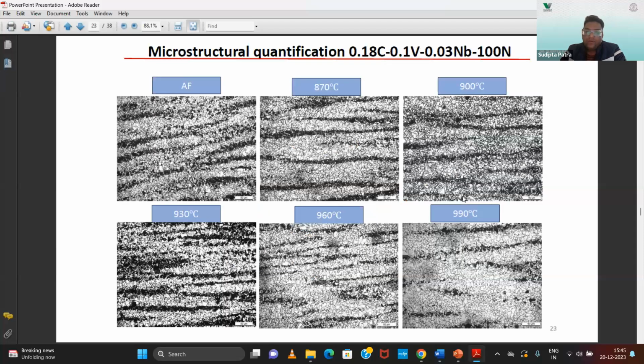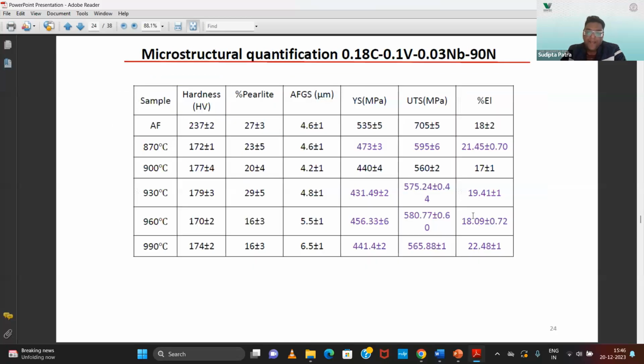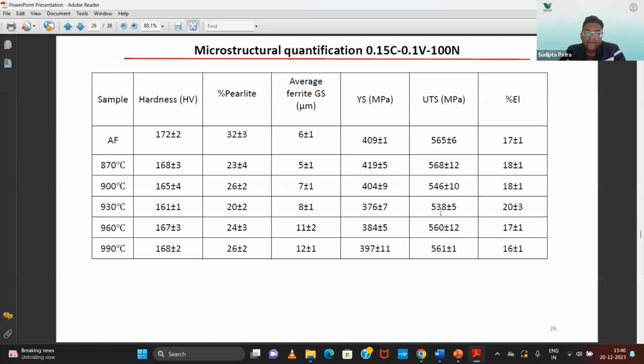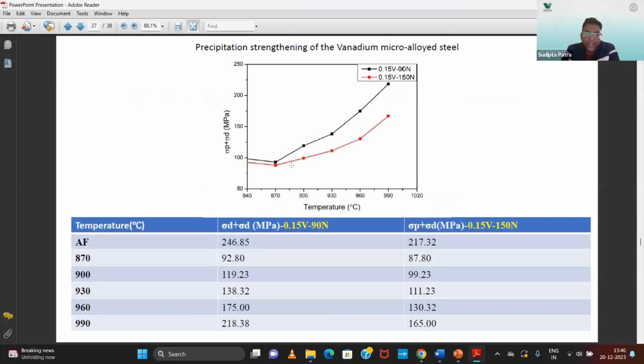So here we have also tried the combination of niobium and vanadium. Here also we could observe very good grain refinement as well as the precipitation strengthening effect. And here also we could get around 460 to 470 MPa yield strength with good elongation and UTS.